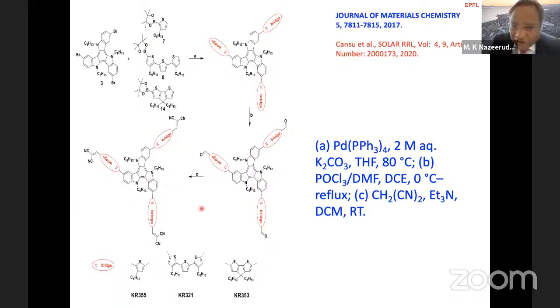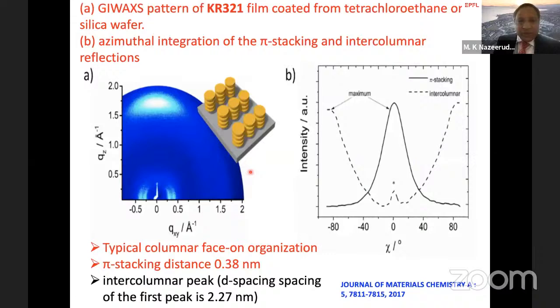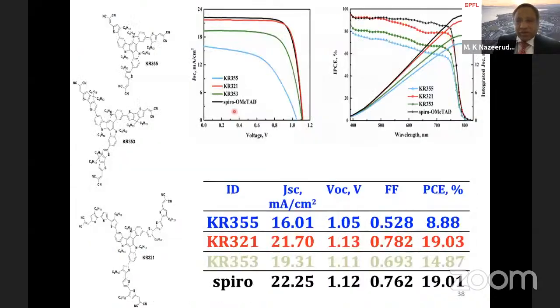There are three functionalities in this design concept. We have a disc-type core molecule, which is attached to three arms with sulfur groups, with thiophene groups as before. The purpose here is to have these cores stack one on top of the other, so that the hole transporting material works without dopants. The cartoon shown here illustrates how the hole transporting materials stack one on top of the other, forming a columnar-shaped hole transporting material on top of the perovskite material.